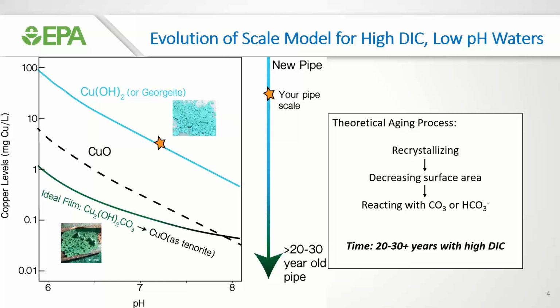So when it comes to controlling copper levels, perhaps the most important thing you get from this, and this is something we talk about all the time, is that copper levels change with time. There's an aging effect. And so this diagram is simply showing copper levels versus pH as a function of age. So basically, when you get your pipe and you start out with fresh surfaces, you start out with the solubility somewhere on the light blue line here that is represented, we think, by either cupric hydroxide or Georgeite, which are 2 amorphous solids, either one of them. But the point being is that they're relatively soluble.